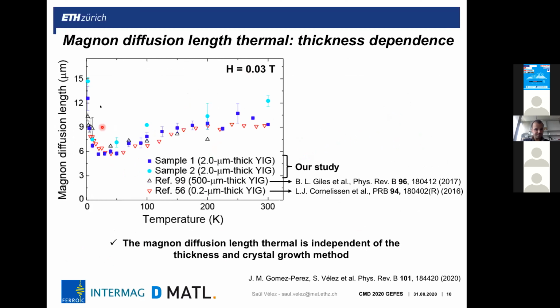Interestingly, we also observe that when we compare our results on thermal excitation with the ones in the literature for other YIG thicknesses, or even different fabrication methods of the yttrium iron garnet, we observe that the magnon conductivity is the same, which means that the thermal magnon transport is a universal effect that doesn't depend on fine details of the growth conditions of the yttrium iron garnet or even the thickness.